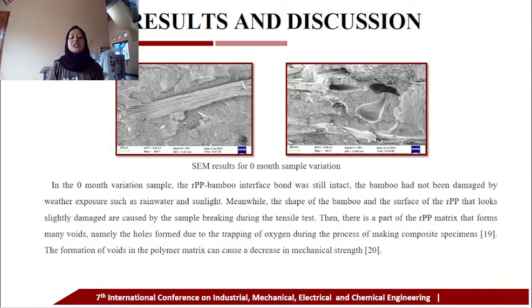And then this is the result for the no exposure sample. In the no exposure sample, the recycled polypropylene bamboo interface bond was still intact. The bamboo had not been damaged by weather exposure such as rainwater and sunlight. Meanwhile, the shape of the bamboo and the surface of the recycled polypropylene that looks slightly damaged is caused by the sample breaking during the tensile test.